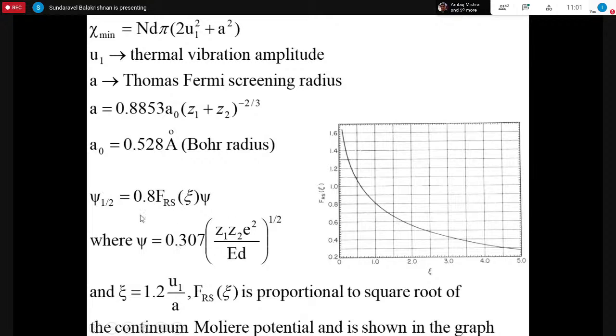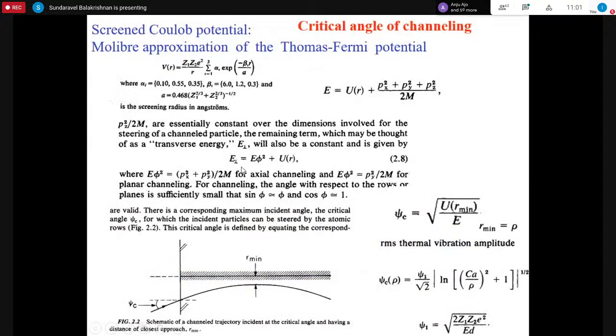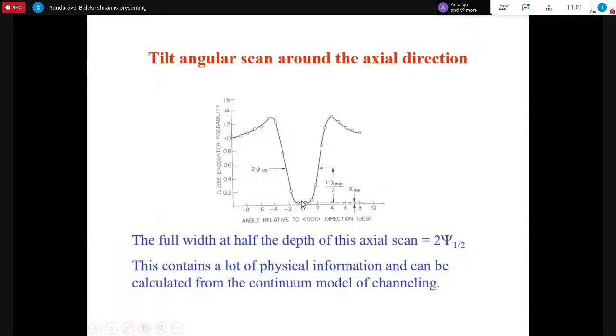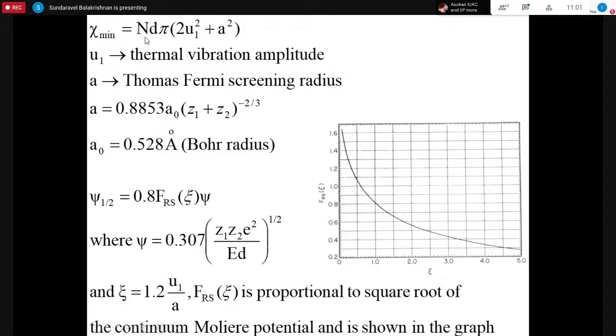That psi half value, one can approximate with this continuum Moliere potential, and it is given by this expression. The ratio between the minimum yield and this random value is chi minimum, and that is proportional to the number density of atoms, N. d is the distance between two atoms along the string, u1 is the thermal vibration amplitude, and a is the Thomas Fermi screening radius. Once you know the atomic density and thermal vibration amplitude for that specific crystal, then theoretically you can calculate this chi minimum value, and if the experimental value is close to this,